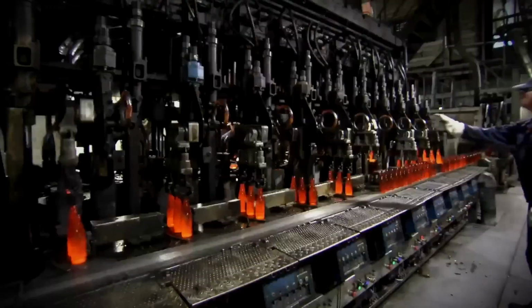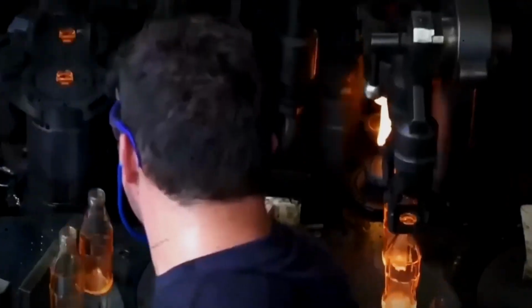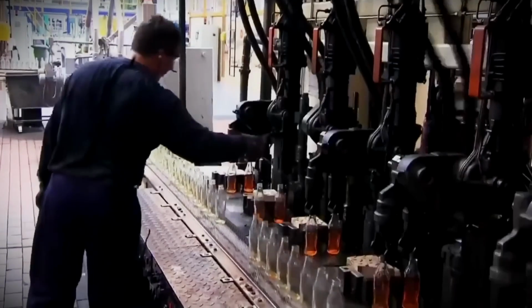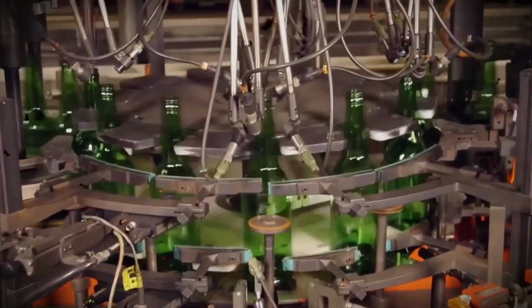Then, every single bottle faces automated inspection. High-speed cameras check for cracks and defects. Infrared sensors detect stress patterns. Bottles must withstand at least 90 pounds per square inch internal pressure. Any failures get crushed and recycled back to the batch house.